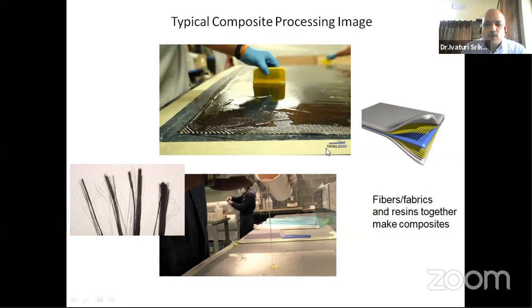So today, as I told, most of the reinforcement phases used in aerospace systems are carbon fiber reinforcement. A typical image I have shown here. Carbon fibers are basically PAN, polyacrylonitrile fibers, which are drawn in the form of fibers. PAN is a polymer precursor, like this kind of liquid only, which is jetted through small orifices of around 6 to 8 micron diameter and quenched. The moment it comes out, it is quenched and then heat treated to 2000 degrees centigrade. So finally they get pure carbon in the form of fiber. The specialty of this carbon fiber is its density is around 1.8 gram per cc and strength is almost 5600 MPa. So if you compare it with iron, which was previously most popular as a structural material, it has almost 2 to 3 times better strength than iron with density almost 3 times less, because its density is only 1.8.